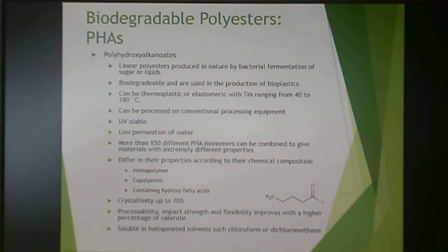There are more than 150 different PHA monomers that can be combined to give materials with extremely different properties. They differ in their properties according to their chemical composition, just like any other polymer we've talked about up to this point. You can have homopolymer, copolyester, and they can also contain hydroxy fatty acids, and hydroxy fatty acid is shown here. They can have crystallinity up to 70%. Their processability, impact strength, and flexibility improve with the higher percentage of valerate, and that is what is indicated here. This is valerate. They are soluble in halogenated solvents such as chloroform or dichloromethane, which also makes them good for fiber properties.